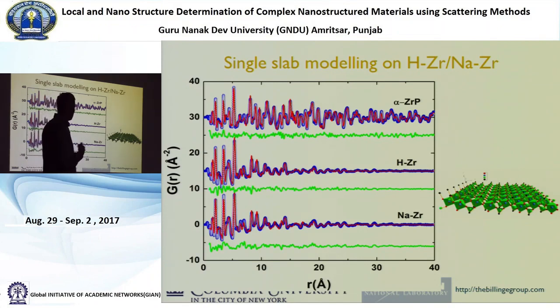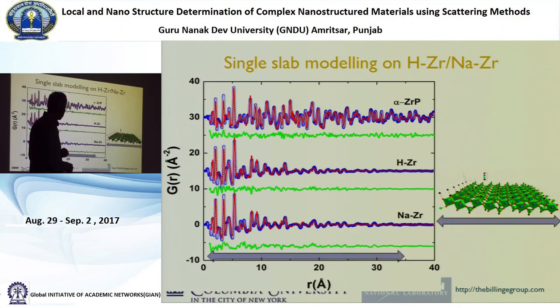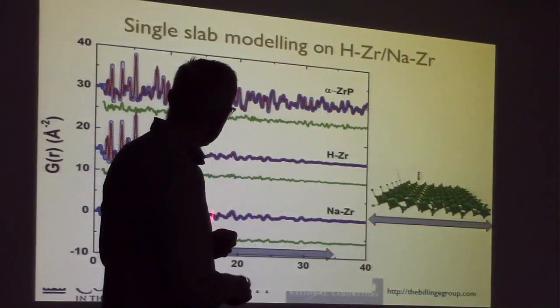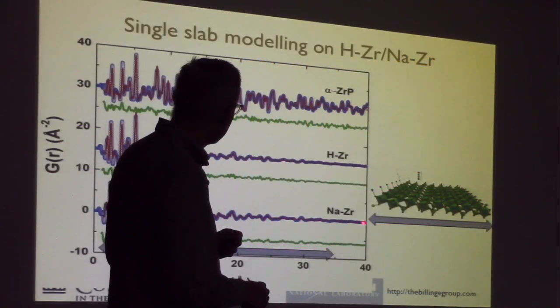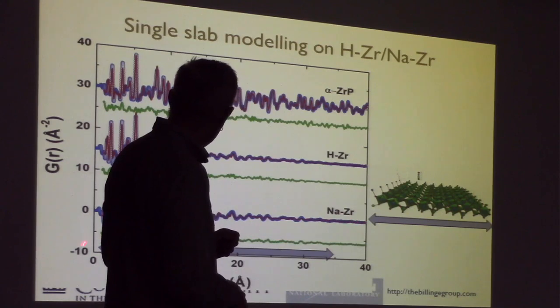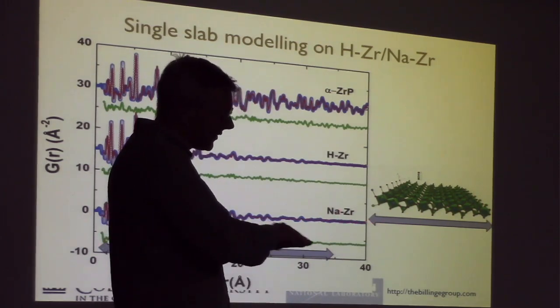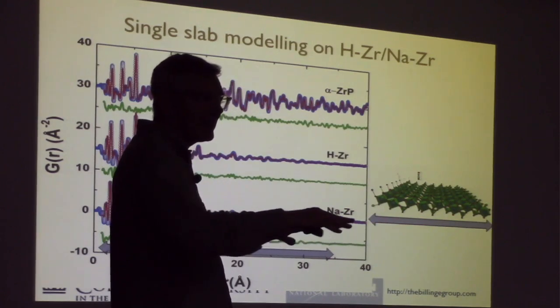And we've been writing new software programs now that are able to do these finite size objects. So we were able to do it. So this is what the layered material looks like. And you can see the peaks here, they extend out here and the signal is almost gone. So where the signal disappears here, that's the range that the layer is actually coherent over.